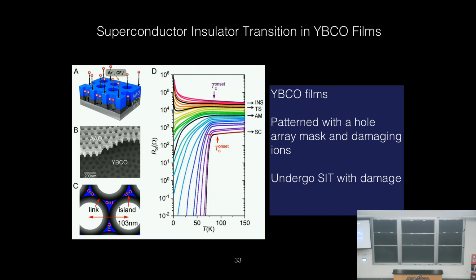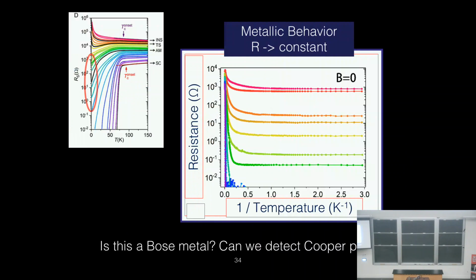Now, what was done, and I believe this was Jimmy's idea, was to take these aluminum oxide substrates, pull off the oxide, which has this holy pattern, put it on top of the film, and then rain energetic ions onto the film. Those ions destroy the superconductor that it hits. The parts that are masked, it doesn't destroy. And you wind up with a film which looks like little islands connected by little necks with holes in them. Very much like the films we were just looking at. And so you could drive it through a superconductor to insulator transition by using more and more damage.